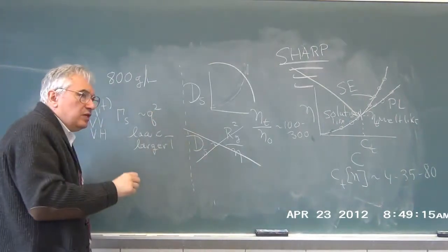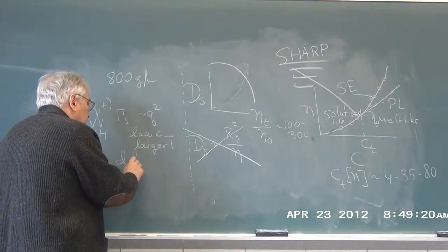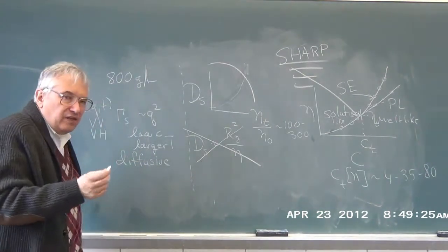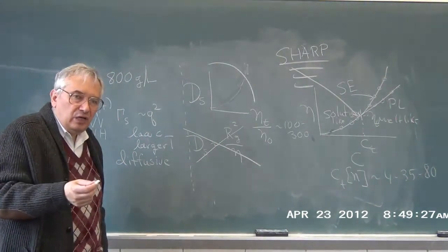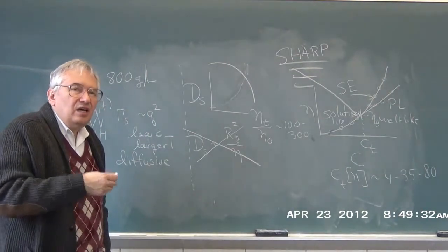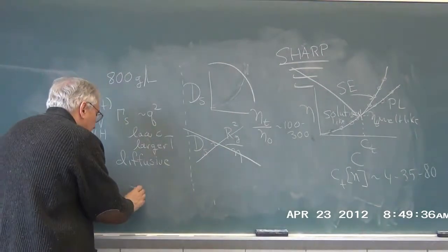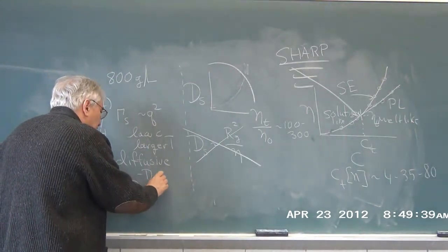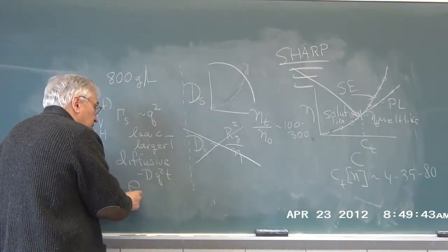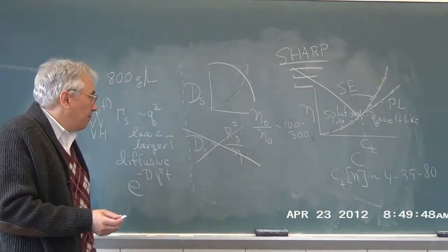The statement that you see a q-squared dependence in the relaxation means that the relaxation is diffusive. That is, if you combine Fick's law and the continuity equation and ask how a cosine in concentration relaxes, it relaxes as a decaying exponential in time, e to the minus D q squared. There's a q from Fick's law and a q from the continuity equation. You get a relaxation that goes as q squared.